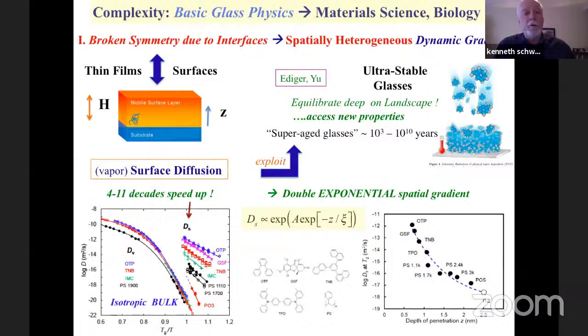And I want to conclude, though, from the general point of view, because I thought there would be students here, that understanding these basic glass physics problems has tremendous implications for material science, and I believe also biology. And this is where a lot of my work is these days. If you go to a thin film, you have broken symmetry due to interfaces, and you have spatial gradients of everything. So for example, Mark Ediger has measured the diffusion near a surface of a thin film and found that the dynamics near the surface can be 4 to 11 orders of magnitude faster than in the bulk. And he has a clever way to figure out what the gradient is as you move away from the surface. And he's found and recently published that it's double exponential. So the diffusion constant depends on an exponential of an exponential as a function of distance from the interface.